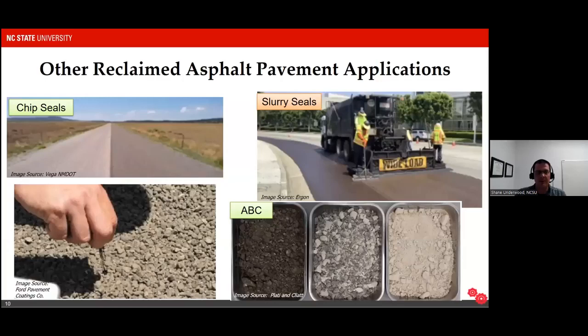There are also examples of using RAP materials in chip seals. Chip seals, again, consist of a thin layer of asphalt binder with aggregate spread on top. And there are examples of using graded RAP materials in those chip seals. That has a lot of benefit because, as you see in the image on the top right, we have a RAP-based chip seal. It looks dark in color. It looks like a real paved, dense graded road when it's completed. The citizens like that. It also cuts down on the dust that you will get coming off these chip seals.